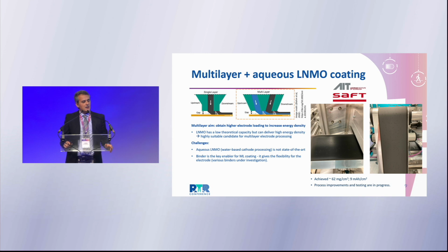The last result that I want to present today concerns the coating itself. Within the consortium, we have two pilot lines, one operated by AIT and one operated by SEA, but we also have a pre-industrial line, sometimes they call it pilot line or pre-industrial line, which is operated by SAFT. And we are investigating new ways of producing and scaling up the material and the coating process. In this slide, you can see some of the results that we achieved with multi-layer coating. So basically applying the coating in a different way.